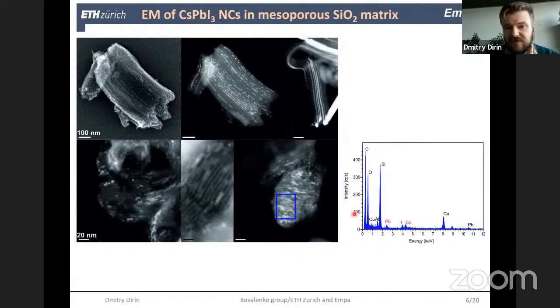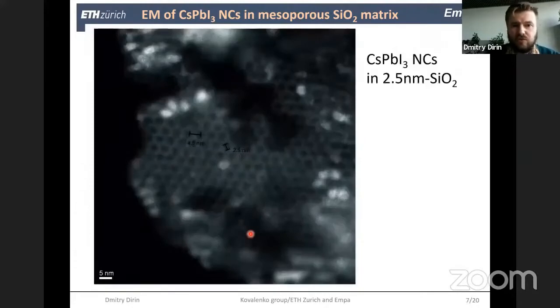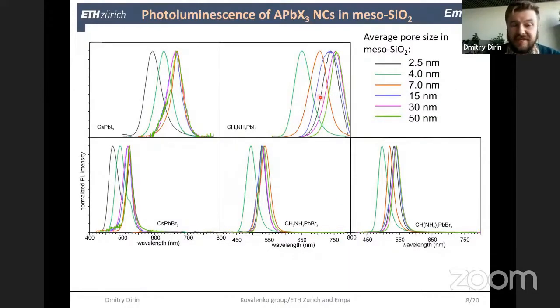And from ETH measurements, we can see cesium lead iodide. We can measure, as usual, the distance between nanoparticles. We can show that the size of those nanoparticles is what we expect for these channels. As usual for semiconductor nanoparticles, we can tune the size of nanoparticles, and therefore we can tune the peak photoluminescence position by tuning the size, if we use mesoporous silica with different sizes of channels.